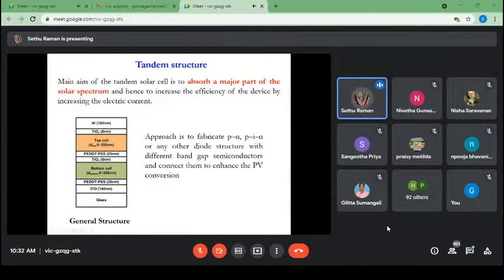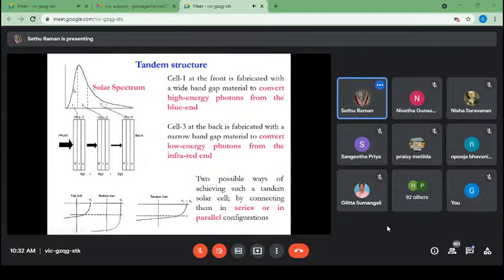So this approach is to fabricate a PN, PIN, or any other diode structure with different band gap semiconductors. Why are they choosing this tandem-like structure? Cell 1 is absorbing the first part of the solar spectrum, and cell 2 is absorbing the second part and then the third part. So the ultimate aim is to absorb the maximum of the solar spectrum. That is the reason cell 1 at the front is fabricated with a wide bandgap material to convert high energy photons from the blue end, and cell 3 at the back is fabricated with a narrow bandgap material to convert the low energy photons from the infrared end. So they are capturing more solar energy, and once they capture more solar energy, they convert it in an efficient way. That's why they are doing it in a stacking structure. This is called a tandem structure.